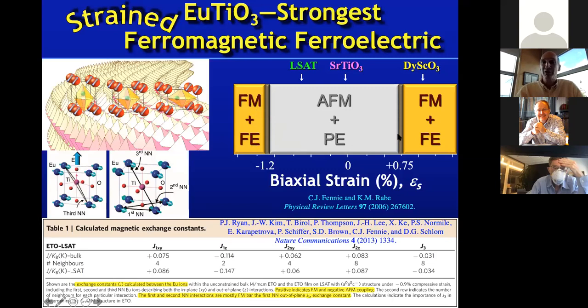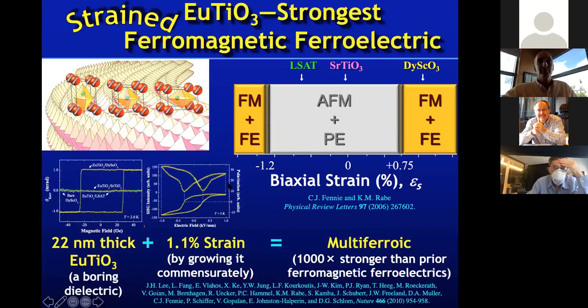Okay, so I've given a long-winded explanation of the inner workings of the material. How does this look in experiment? What we saw in experiment, and we did many control experiments too, is that when we looked at the unstrained europium titanate on strontium titanate, as well as biaxial compression on LSAT, and this is a magneto-optic Kerr effect, neither of those show any evidence of ferromagnetism. Whereas when we strained it in, these are all commensurate films, so we kept them thin, in biaxial tension, then you can see from the magneto-optic Kerr effect that there's a robust ferromagnetic state. We also looked at the ferroelectricity.